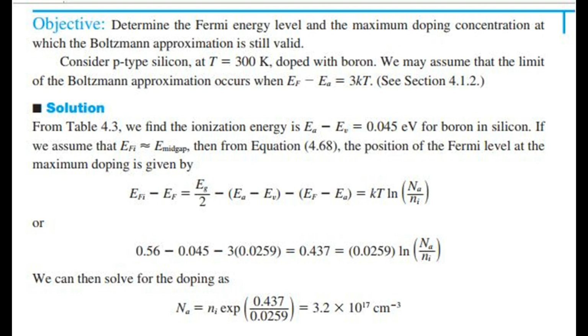Objective: determine the Fermi energy level and the maximum doping concentration at which the Boltzmann approximation is still valid. Consider p-type silicon at temperature T equals 300 kelvins, doped with boron. We may assume that the limit of the Boltzmann approximation occurs when EF minus Ea equals 3kT. See section 4.1.2. Solution: from table 4.3, we find the ionization energy is Ea minus Ev equals 0.045 electron volts for boron in silicon. If we assume that EFi is at midgap, then from equation 4.68, the position of the Fermi level at the maximum doping is given by the equation. We can then solve for the doping.